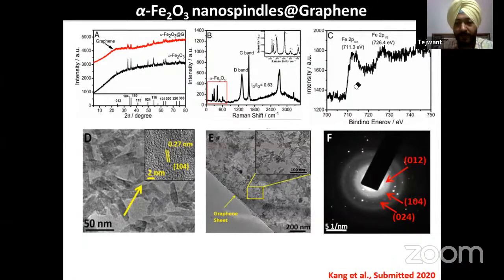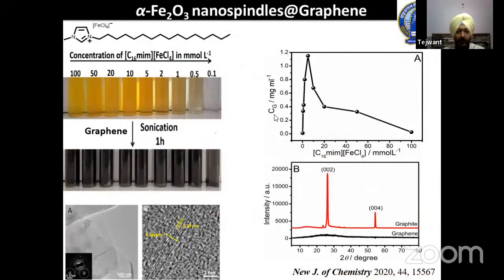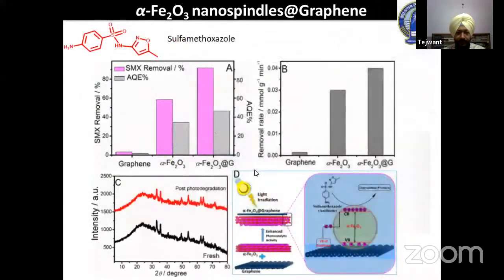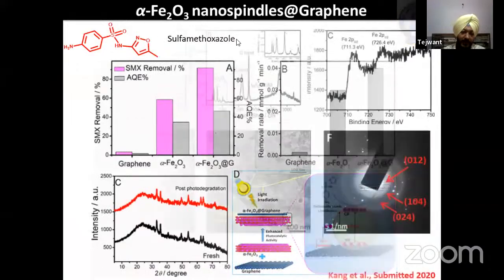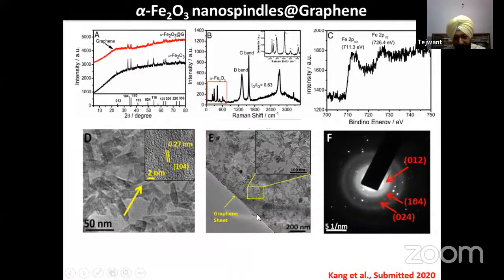Further, this has also been established with the help of XPS measurements. The TEM images have shown the formation of spindle shaped alpha Fe2O3 nanoparticles at the surface of graphene, where the lattice planes corresponding to alpha Fe2O3 nanoparticles have confirmed their presence. So the prepared material which I have shown you there, here one can see the graphene sheet and the presence of a large number of alpha Fe2O3 nanoparticles on the surface.